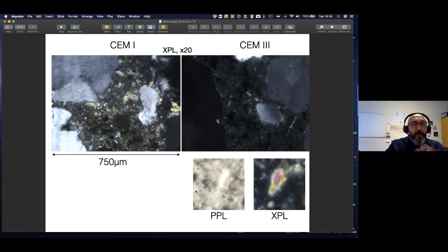Here, another example, differentiating between ordinary Portland cement and slag cement. You see the ordinary Portland cement microstructure looks quite bright. There are tons of fireworks going on there, right? I mean, you see a lot of colorful inclusions here and there. But on the right-hand side, the CEM3 slag cement paste is rather dull and boring. You know, it's quite dark. Why? The main reason, if you've been studying cement hydration, of course, is that CEM1 develops a lot of calcium hydroxide crystals. On the contrary, CEM3, especially CEM3B, when you have a lot of slag grains inside, you don't have a lot of calcium hydroxide.